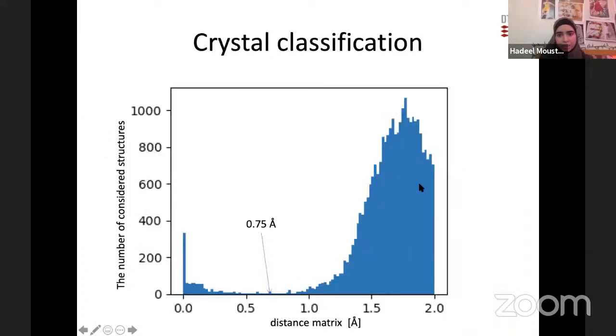After that, we make a distribution of our distance matrix, where the y-axis is the number of the considered structures, and the peak at 0 represents the diagonal of the distance matrix. And as we can also see, we are dealing with two parts. The first part where the materials are close to each other and the part where they are far away from each other. For that, it makes sense to make a separation, and we did that at 0.75 angstrom.